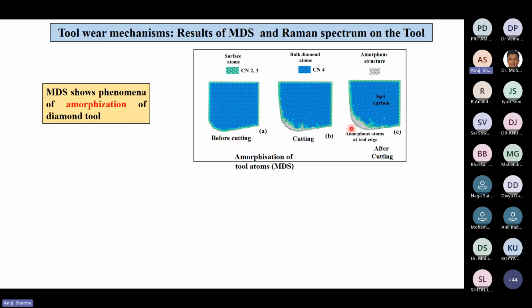It was also seen with the help of coordination number. Here the coordination number in the bulk is 4, and for the surface atoms it showed 2 and 3. But here we can see that an amorphous layer is being generated. Basically the amorphous layer weakens the cutting edge and it dominates the tool wear mechanism.